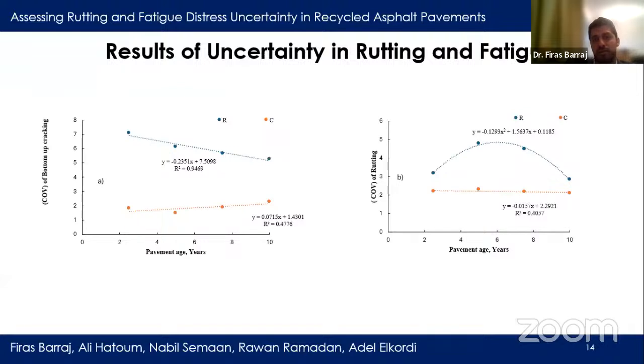So as a result, for the bottom-up cracking, the results indicate that the coefficient of variation between simulations of 500 RAP mixes decreased linearly with time from 7.2% after 2.5 years to 5.28% after 10 years. Conversely, the coefficient of variation of the control mixes appears to increase linearly over time, rising from 1.83% after 2.5 years to 2.3% in 10 years. Importantly, it's noted that the uncertainty in the cracking performance of RAP mixes consistently exceeds that of the control across the pavement design life. And this was expected due to variation in the material of unclassified RAP.